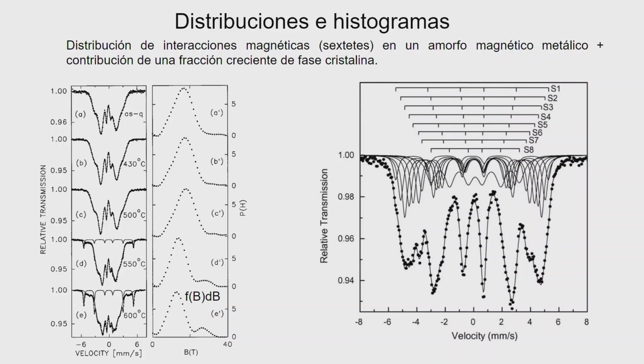Probably if you put two, you would increase your electric field gradient. But after you fill half of the first coordination sphere, then the electric field gradient will begin to reduce. If finally you have 8 near neighbors, for instance, in a cubic centered system, then your electric field gradient will be 0 again. Okay, so the correlation between hyperfine field and quadrupole interaction, in principle, should not be linear.